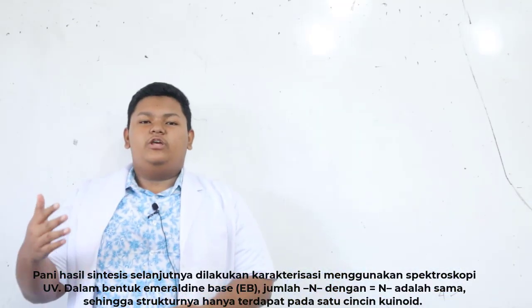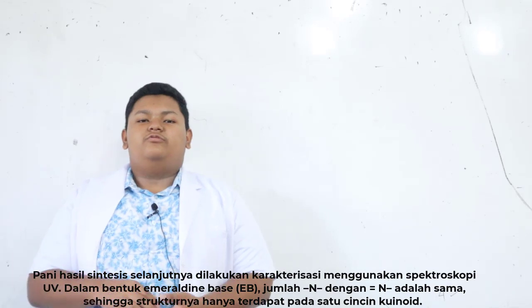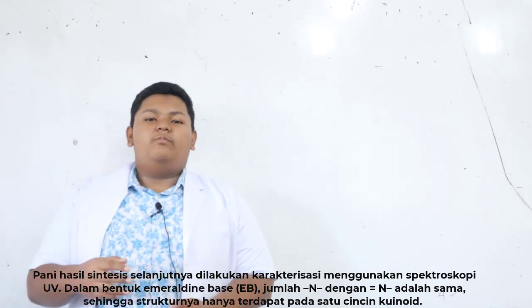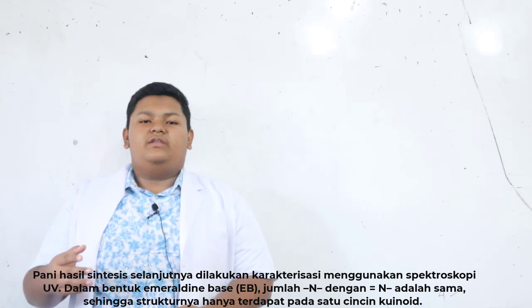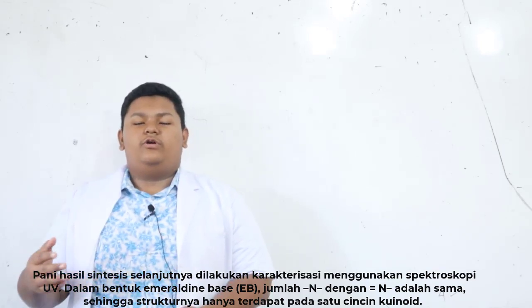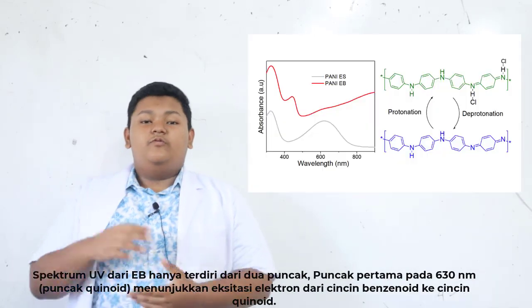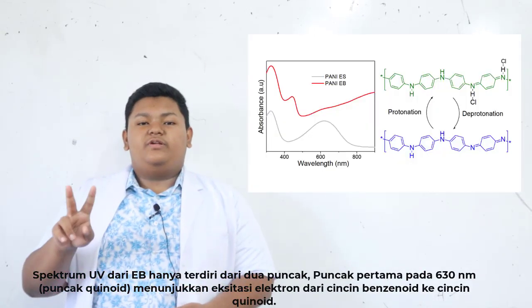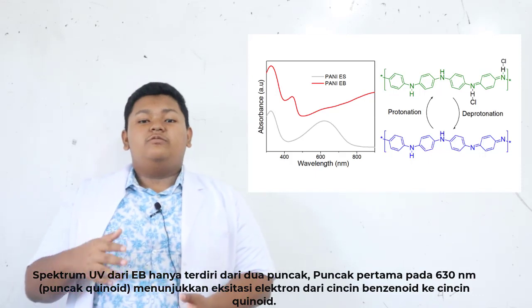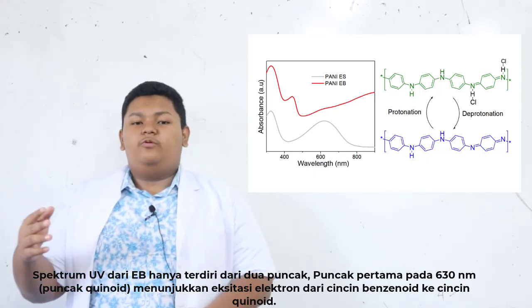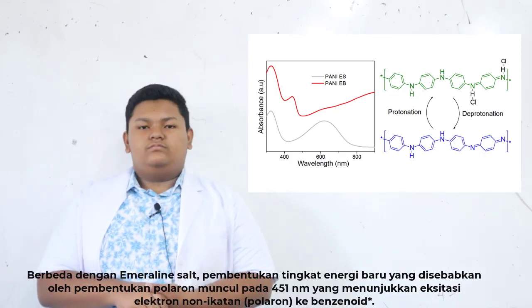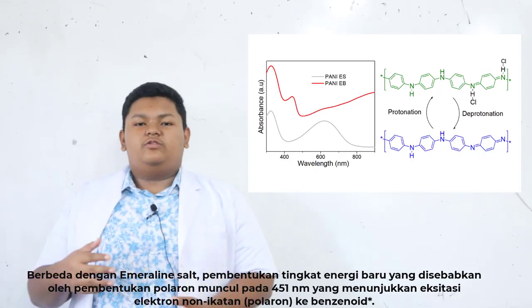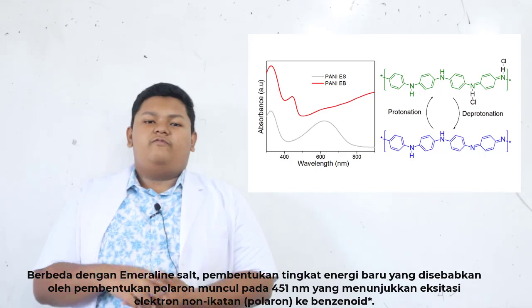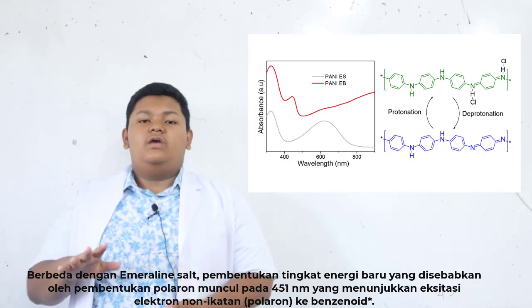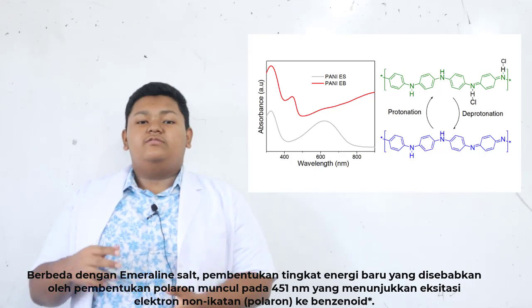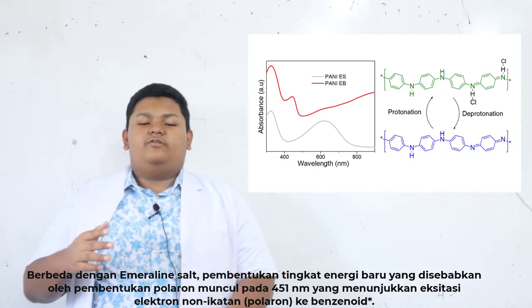The synthesis result of polyaniline was characterized using UV spectroscopy. In the form of emeraldine base, the number of N with double bond and N is the same, so the structure has only one quinoid ring. The UV spectrum of emeraldine base consists of only 2 peaks. The first peak at 630 nm shows the excitation of electron from the benzenoid ring to the quinoid ring. Unlike the emeraldine salt, the establishment of a new energy level caused by the formation of polaron occurs at 451 nm, which indicates the excitation of non-bonding electron to benzenoid.